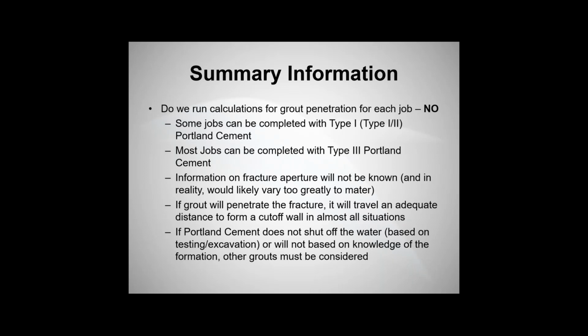So what can we say when it comes to choosing the right type of grout based off of that? Number one, as Britt said, some grouting jobs can be completed with type 1 or type 2 Portland cement, which are about the same for grouting purposes. They'll fill the larger fractures, and that may be all that's needed. We assume that most jobs, based on experience in the grouting industry, can be completed with type 3 Portland cement for filling of fractures. As you can see, you can get to a fairly small fracture size for filling and travel a fairly far distance.